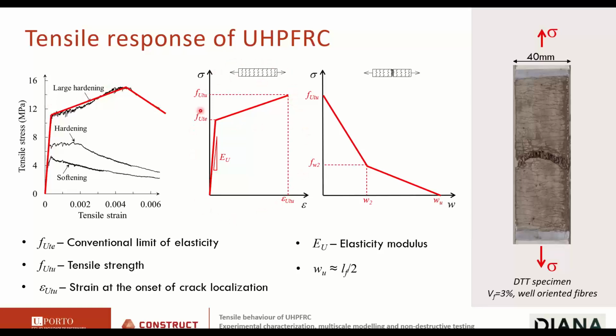This part of the constitutive law describes the tensile stress versus strain behavior of the material before you get to the peak stress, because at peak stress, one crack will localize somewhere along the specimen, and then all the deformations will be localized on this crack. So from the peak onwards, instead of a stress-strain model, we need a stress-crack opening model, like what we do for concrete. In the context of finite element analysis, this part of the constitutive law is independent of the finite element size, while here you need to define a fracture energy and then use the crack band theory to apply in the finite element analysis using continuum elements.